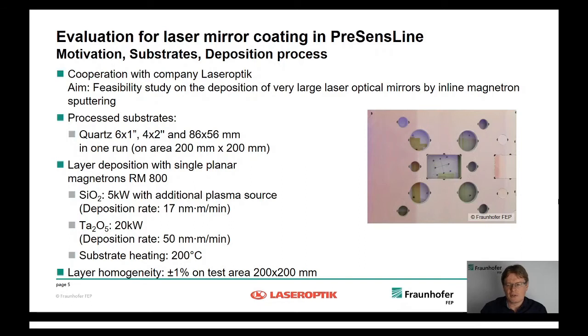The layer deposition was done with our RM800 magnetrons. Here you see the sputter power. We used silicon oxide at 5 kilowatt. The deposition rate was not that high. The priority for us was the layer properties. For tantalum oxide, we achieved a quite high deposition rate. Layer homogeneity was plus minus 1% on the test area, which was enough for this test.